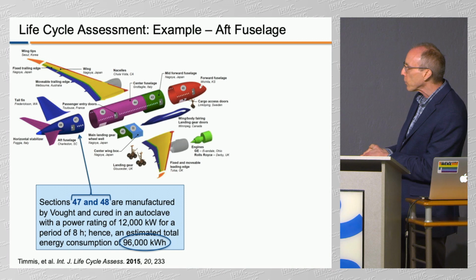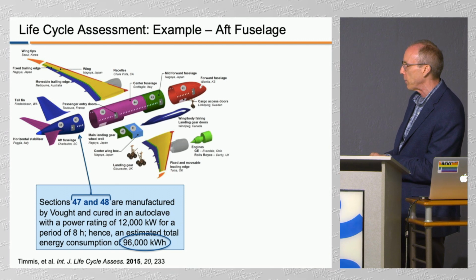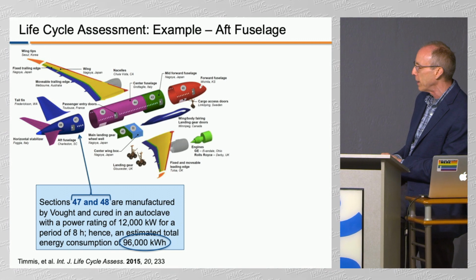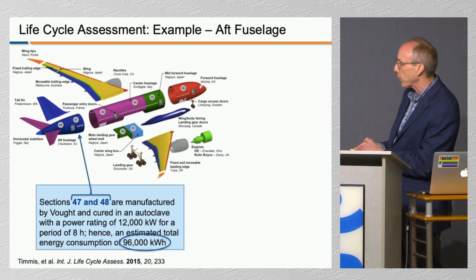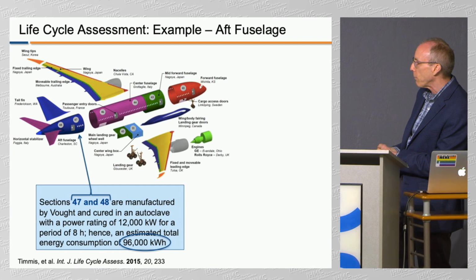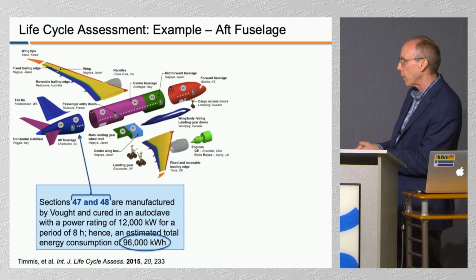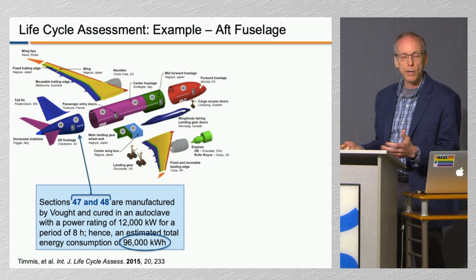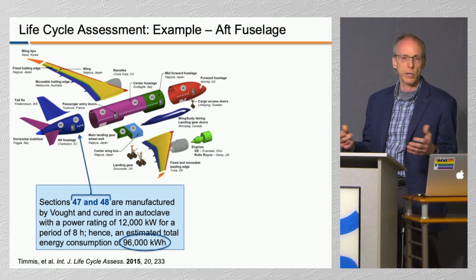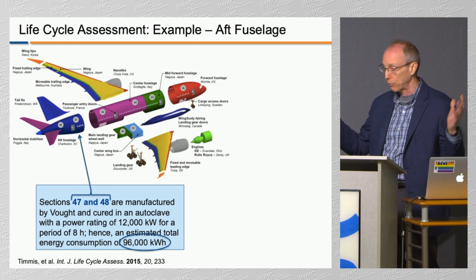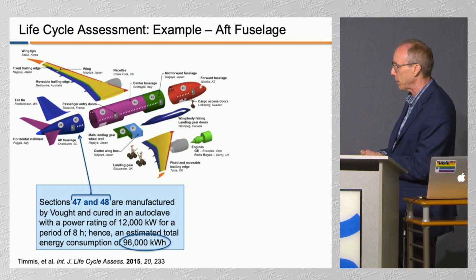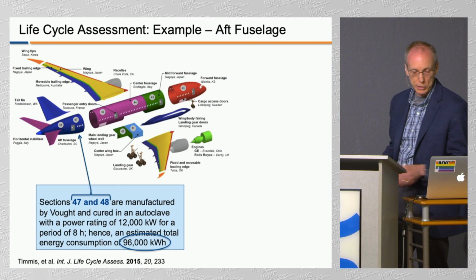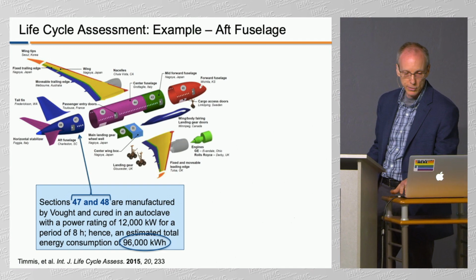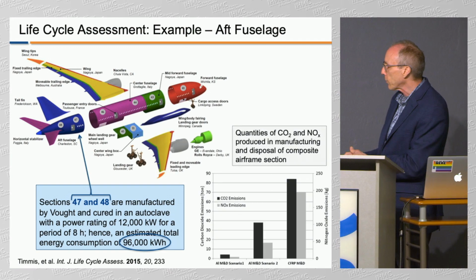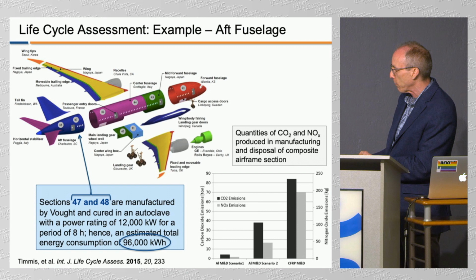Well, the analysis was done on these two tail sections labeled 47 and 48, and those are those sections right there. Basically the composite is cured 8 hours at about 180 degrees Celsius, so very high temperature for a very long time. Hence, a lot of energy goes into this massive part and its curing. And this is a plot that was out of that paper.